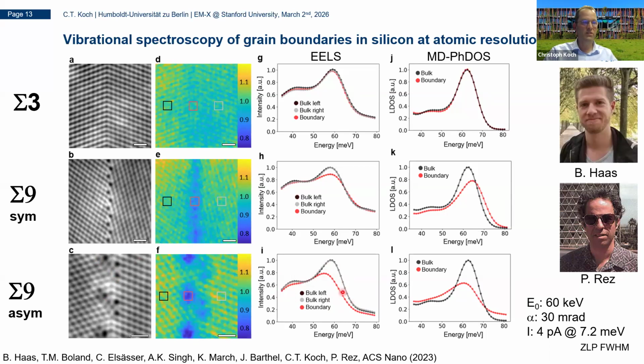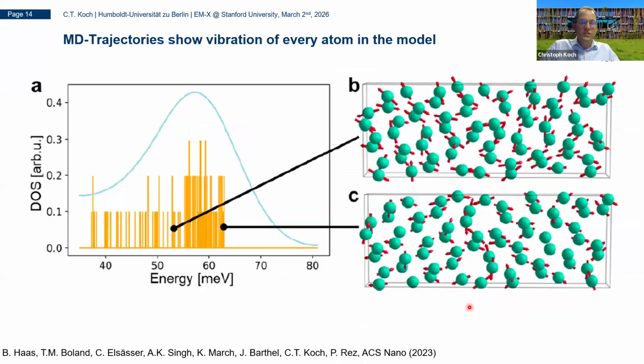The red curve is always the boundary, and the gray and the black one are the grain on the left-hand side and the right-hand side. They actually coincide. And you can see in the MD simulations, this reduction in the intensity of the 60 milli-eV peak is reproduced. So what we learn from this is the MD calculations actually reproduce what we see in the experiment. And so why don't we now work with more than just the energies of these phonon modes, but also the eigenmodes of these vibrations? And that is indicated here.